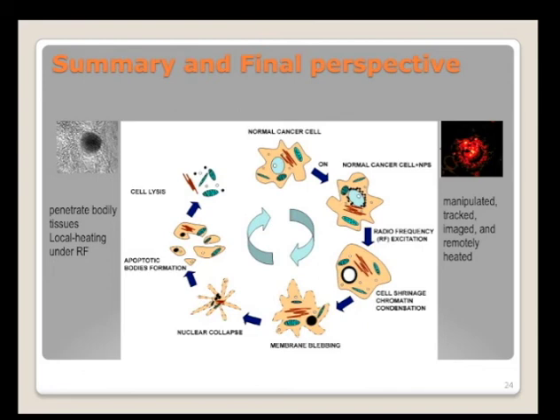Okay. Now to come to the summary, we successfully developed two types of nanoparticles. They're all magnetic. First, carbon-coated iron cobalt alloy nanoparticles. We found the iron nanoparticles more efficient, and they can kill HeLa cervical cancer cells. Second, we combined the magnetic particle with quantum dots, so they have imaging capability. All these particles are nanometer size, usually below 10 nanometer. They can penetrate the cell membrane and even go to the nucleus of cells.